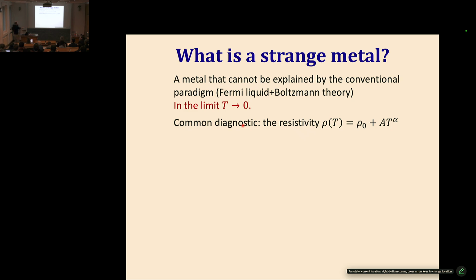The most common diagnostic, just because it's the first thing that you would measure experimentally, is the temperature dependence of the resistivity. What people often observe, which is sort of the first signature of a strange metal, would be an anomalous temperature dependence of the electrical resistivity at low temperature. There's always some constant, which is the T goes to 0 limit of the resistivity, typically due to impurity scattering. But if you look at the first temperature dependent correction to that, that might follow a power law dependence, T to the power alpha.